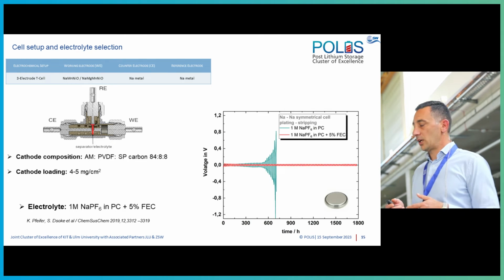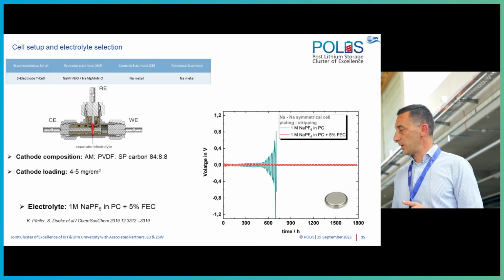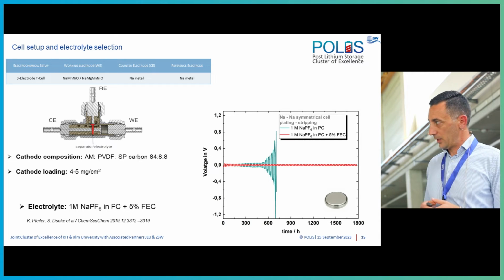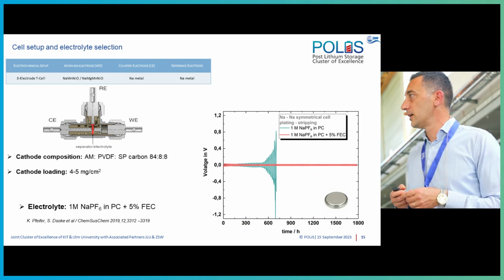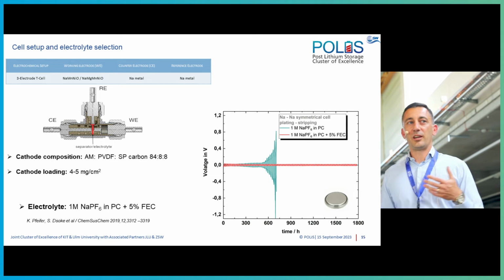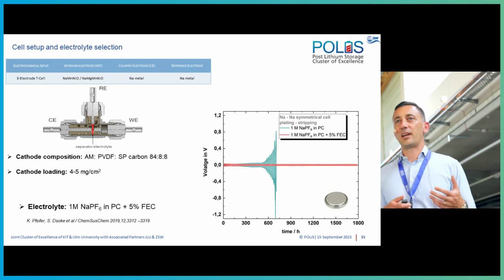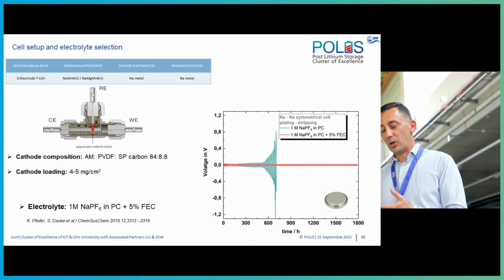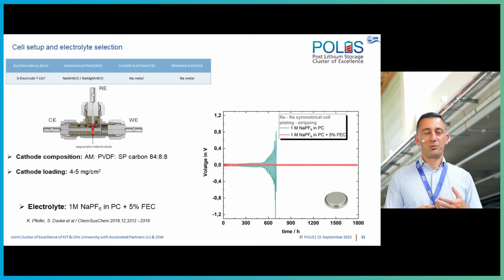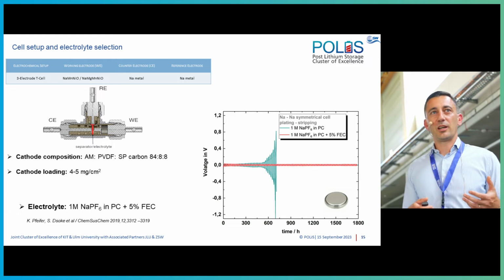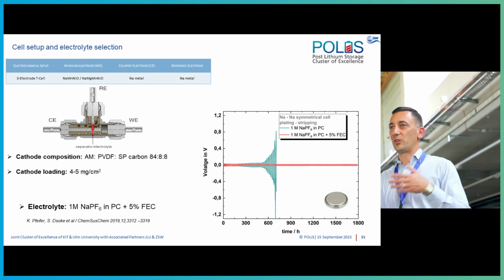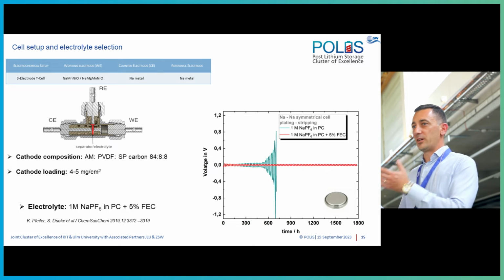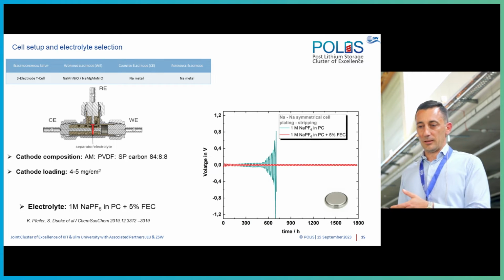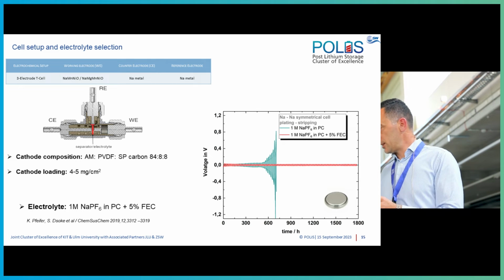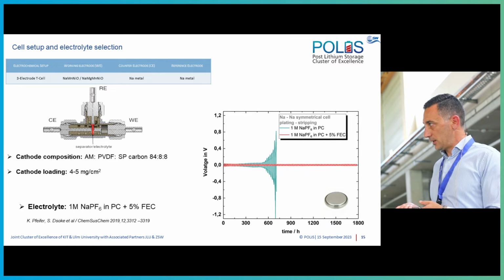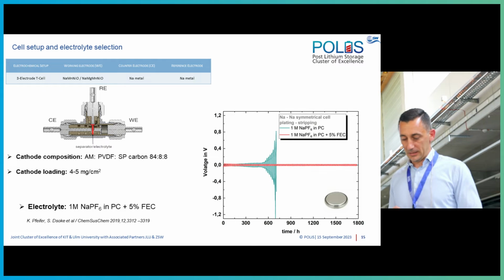The selection of the electrolyte was a little bit more tricky. We were inspired by the work that Sonia did and published in 2019, where actually they proved that the sodium metal can impact directly the performance of your cell, and so therefore what you are actually looking at in terms of degradation is more related to the degradation of sodium metal rather than the degradation of your working electrode. So to prevent that, we included a small amount of FEC.